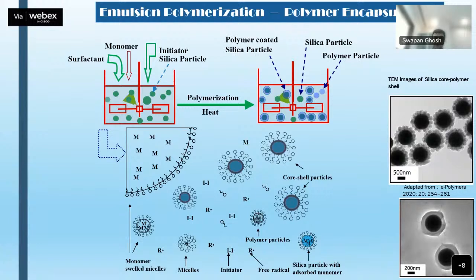So now the question is, how can you force the monomers to prefer the silica particles and not the free micelles? Because at the end of the day, when we conduct the reaction, our purpose is that whichever silica particles, whichever amount we have used, all of them should be coated. And if there is free polymer, the meaning is that a majority of the silica particles will remain free. And I told you in the beginning that the silicon oxide particles, when used in the beginning, are already modified.